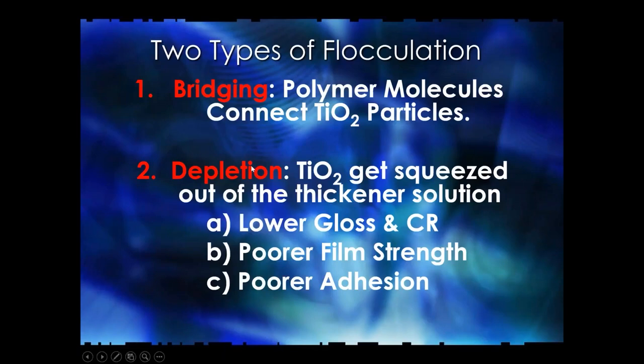Those are things that we're concerned about. But you have to be concerned that these polymers you're adding don't act like stickies and hold things together. And there are ways to make sure that that doesn't happen. There's also another thing called depletion. And that's simply like walking through New York City. There's a big crowd. Everybody's bumping you in together with your little group, and your little group can't stay dispersed out on the sidewalks, and they just get pushed in together because there are people bigger than you pushing you around. When you have depletion flocculation, you'll get lower gloss, lower contrast ratio, poorer film strength, and poorer adhesion. So there are some consequences as a result of doing that.